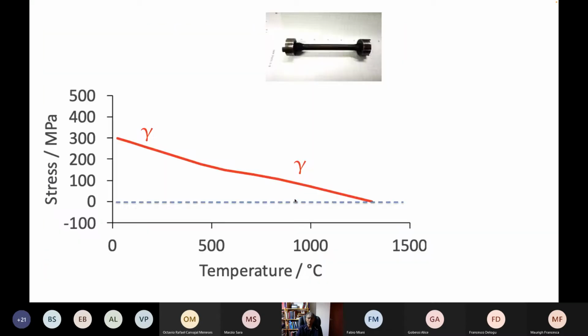Okay, so imagine that we have a sample here, which is an austenitic stainless steel and remains austenitic at all temperatures. So this was a classic experiment done in 1977 by Alberry and Jones, where they heated this tensile sample to a high temperature and then physically fixed it and allowed it to contract. And as it contracts, you get an accumulation of stress. If it was only thermal contraction, this stress would rise rapidly. But at high temperatures, some of the thermal contraction is accommodated by ordinary plastic deformation. Okay, so the rise in stress is lower than you would expect, but nevertheless significant at about 300 megapascals.